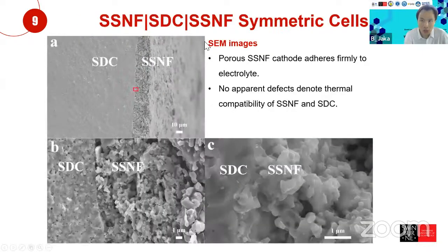Okay, so this one is the figure for the symmetric cell. We make symmetric cells in order to characterize the area specific resistance. In solid oxide fuel cells, if we want to test the cathode performance, we make symmetrical cells and check the area specific resistance as a function of temperature. In the beginning, when we made these using spray coating, we found that everything is well integrated with each other. You can see the interface is quite good, so there are no defects. So there is thermal compatibility between SSNF and SDC.